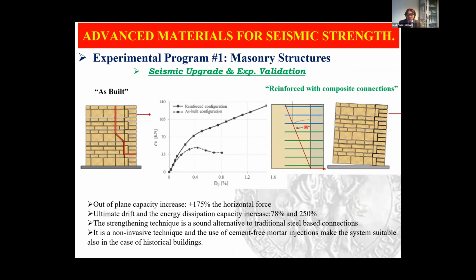And if we compare the behavior of the as-built and reinforced specimen, we could underline a very strong increase of out-of-plane capacity, plus 175%, and also in terms of ultimate drift and energy dissipation capacity, the increases were about 80 and 250%. So this technique was demonstrated to be a sound alternative to traditional steel-based connection, which could have some problems related to corrosion, and also it is a non-invasive technique, and the use of cement-free mortar could be suitable also in case of historical buildings.